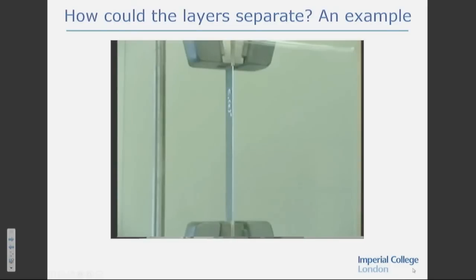What I want you to do is watch what's happening on the edge of the specimen around here initially. So there we go, something started to happen. And you can see it's gradually unzipping. It's actually unzipping right at the mid-thickness. Exactly the same thing is happening on the other side of the specimen. And this is just due to a tension applied longitudinally on that specimen.